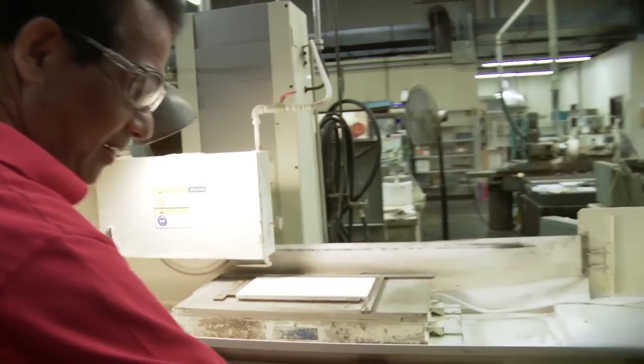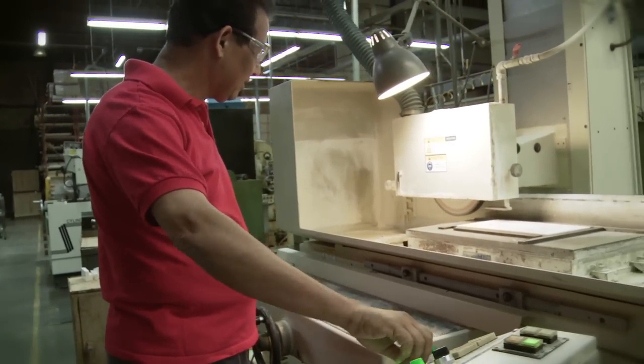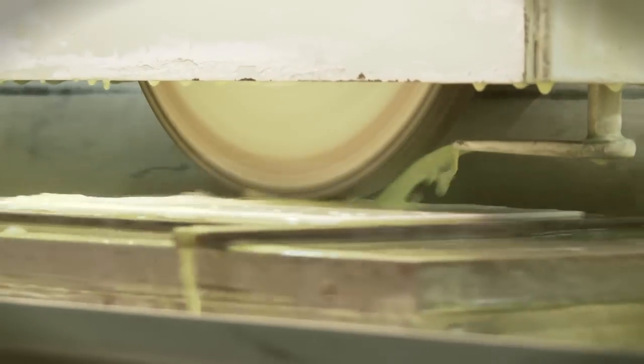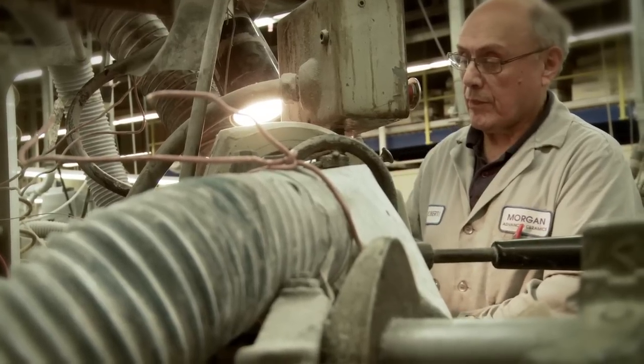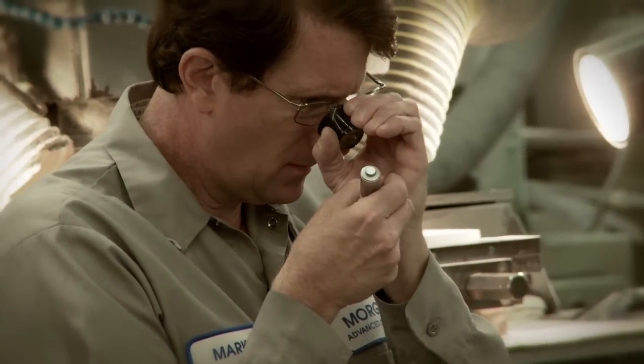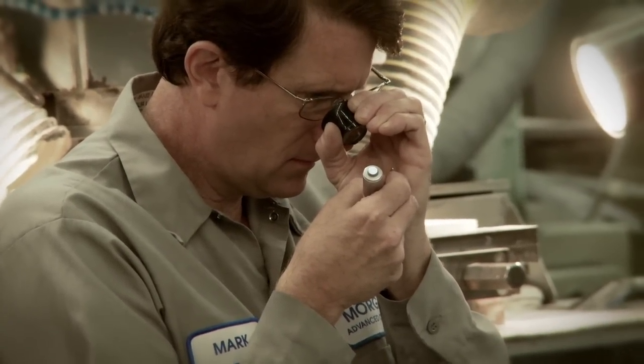Proper machining speeds and generous amounts of water-soluble coolant is critical to the successful machining of Macor glass ceramics. While Macor can be machined with high speed steel tools, it is recommended that carbide tools be used for longer wear resistance.